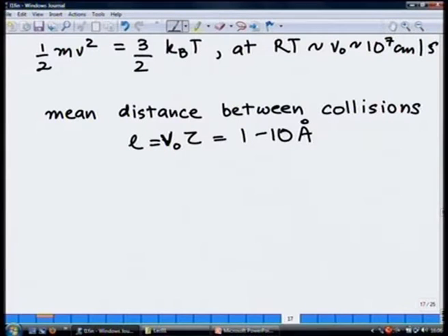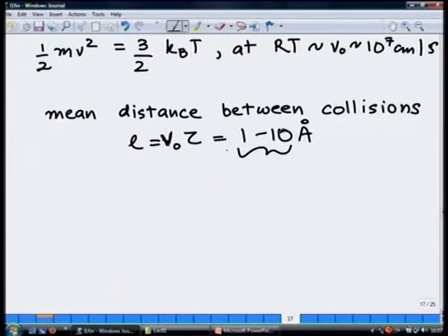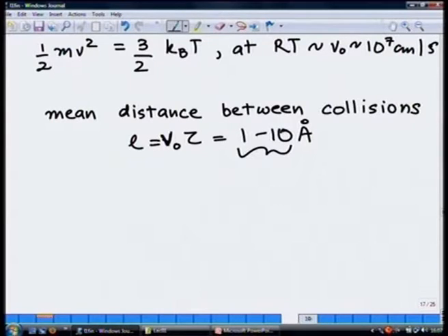So, now this became the proof of Drude theory, that this is a good theory, because interatomic distances are on that order, 1 to 10 angstroms, and since he assumed that the conductivity is arising out of electrons colliding with these ions, and this theory now predicts L on the same order, 1 to 10 angstroms, mean distance between collisions, matching the interatomic distance, it appears that this is a good theory. So, now let us start. This is the basic idea of Drude theory, but what I will start telling you about now is